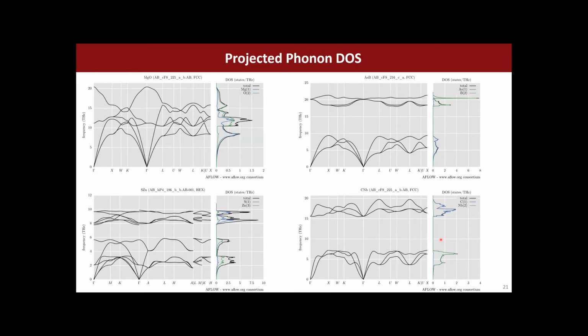By having a large phonon gap, you can also reduce some scattering processes. Boron arsenide, for example, has a very high thermal conductivity, and one of the reasons for that is that they have strong bonds and they have very large mass differences.